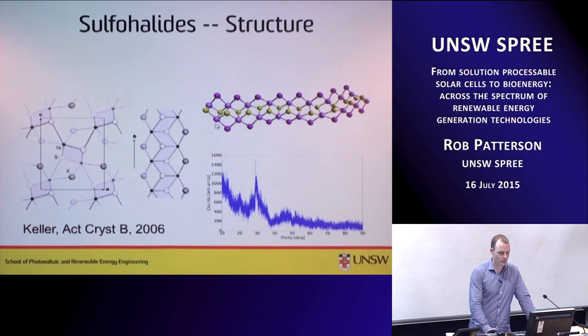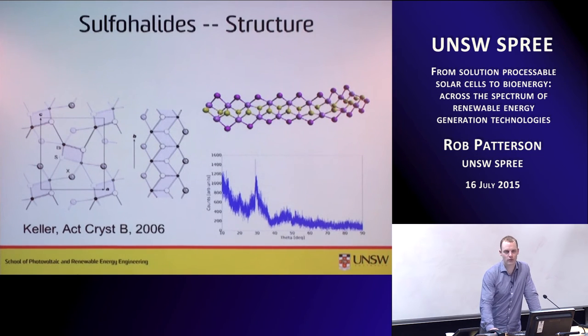And so I've made some of these materials, and our XRD so far is not particularly convincing. But it has peaks in the right places, just the peaks are very small. And we're not sure exactly why at this moment. This is fresh off the press, I made these 2 weeks ago. So it may be that we need to anneal them at a slightly higher temperature, we need to fabricate them at a slightly higher temperature, or it may be that they're just not dry. So we have incorporation of the solvent still in the unit cell, and MoS2 does the same thing if it's not dry.